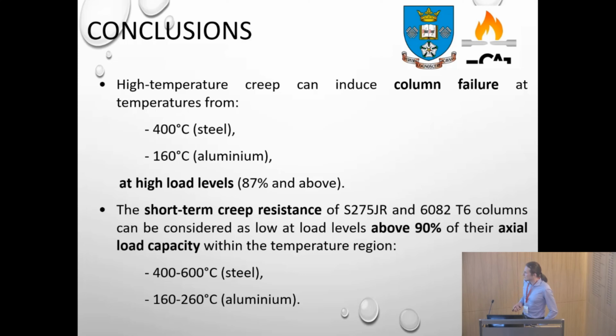And also what's been noted is something that I call the short-term creep resistance, which means that if you test the columns with respect to temporal exposure, the resistance time of these columns is very low, in a matter of 10 or 20 minutes. I would say that's rather low, when the load levels are above 90% of their axial load capacity. So this is something that's confirmed on steel S275 and the tested aluminium alloy, but I would say that the conclusions would be roughly the same for any other carbon steel alloy that's used in practice today.